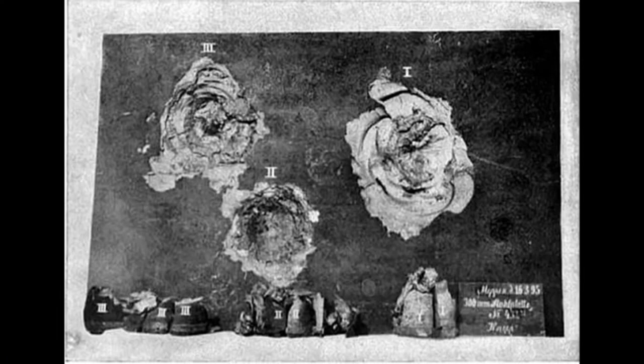This would be further refined in the early 1900s with slight changes to the steel formula that now included not just iron, carbon, nickel and chromium, but also trace elements of manganese, silicon, phosphorus and sulfur. This allowed the back of the armour to retain more toughness, which reduced spalling and cracking and overall increased the effectiveness by about another 10%, thus giving the armour that would be used on most ships in the Dreadnought race approximately a 30% advantage in protection compared to Harvey armour.